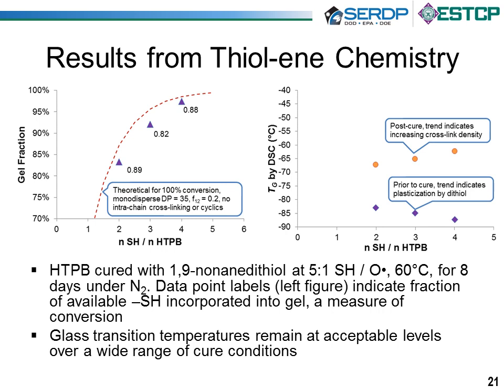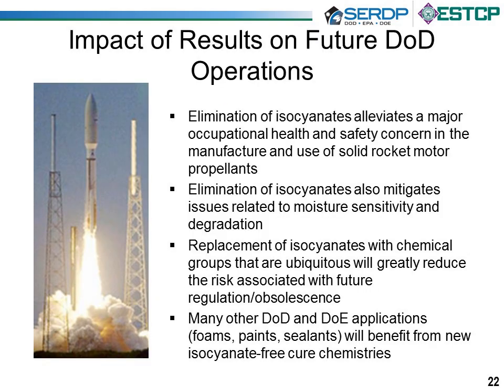Now, this seed project is one of several that's being funded by SERDP in this area, and all of them, regardless of which sort of efforts we find to be successful or not, anything that is successful is going to have very significant benefits for DoD operations, and this is really what I want to focus on for a minute. Elimination of isocyanates not only gets rid of the significant occupational health risk that's associated with these materials, but also it helps to solve some other issues in manufacturing of propellants. So isocyanates tend to be moisture sensitive, which means that if you manufacture on a day with high humidity and on a day with low humidity, you're prone to get different kinds of results. Replacing the isocyanate chemistry can potentially eliminate that kind of variability issue.